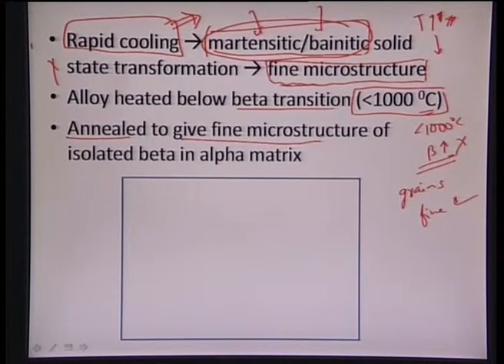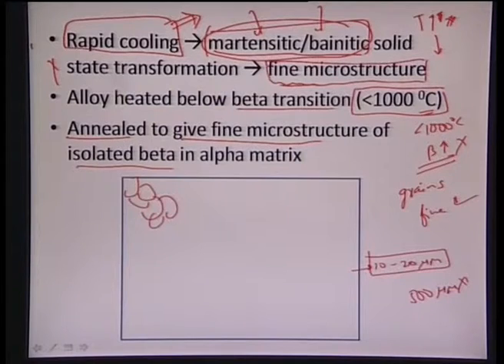In this particular case, we have isolated beta in an alpha matrix. So that is what is happening now. We are not letting the beta form to a large extent. So we see very fine grains which can form, and these fine grains are on the order of around 10 to 20 microns. Instead of going up to more than 500 microns, they are no longer 500 micrometers in diameter. They remain in the 10 to 20 micrometer regime. And once we have this fine alpha regime, we have alpha grains, and we see that the beta is forming within it. So we will see some beta forming here and there, but it is again scattered and very fine.